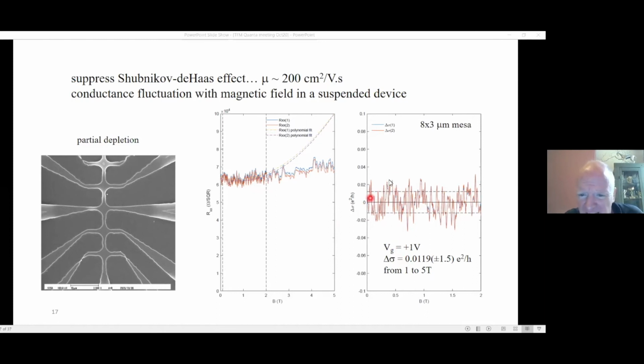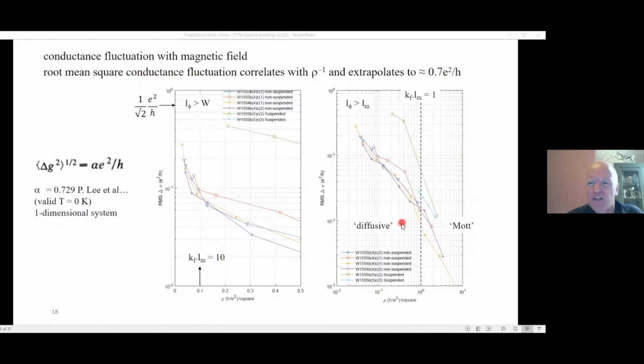And we can calculate this in terms of e squared upon h. It's quite small here. Question is, what's causing that? There's a lot of data on this next slide. I've plotted the root mean square conductance fluctuation as a function of resistivity of the device. This is at constant temperature. What we'd normally do is do a temperature dependence to this. But what I've done is I've plotted out this data as a function of resistance.